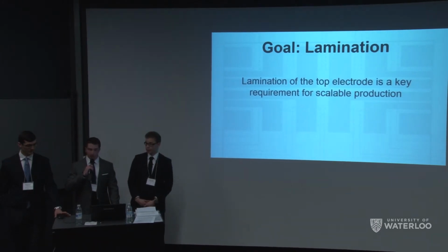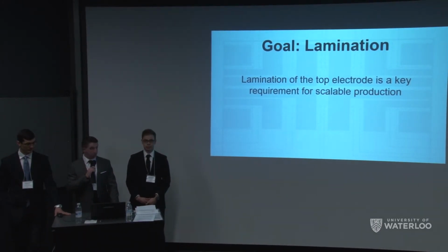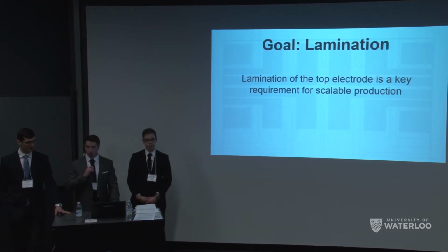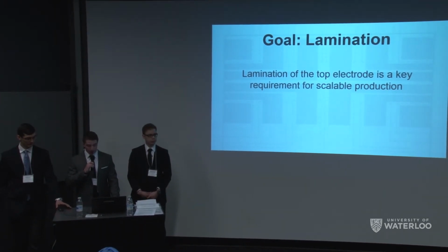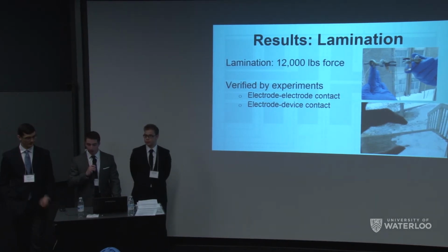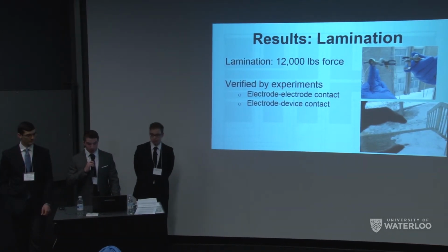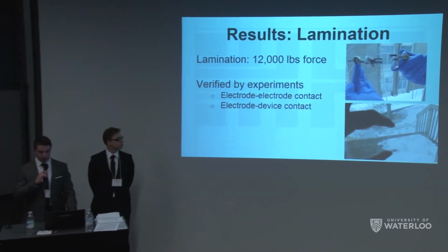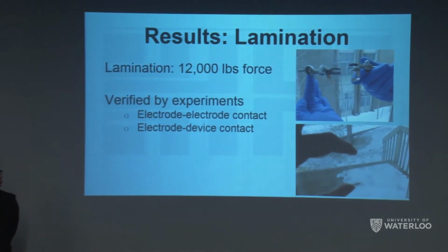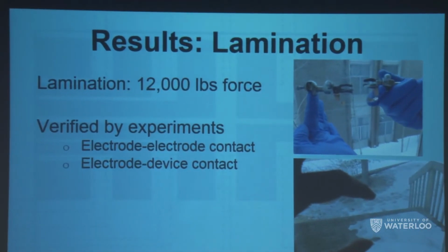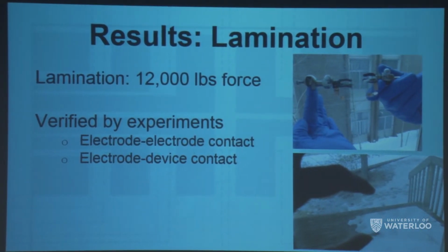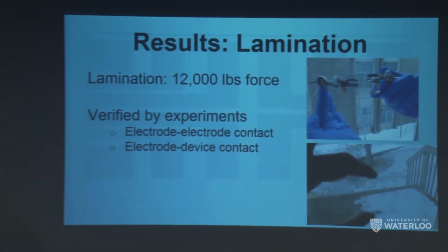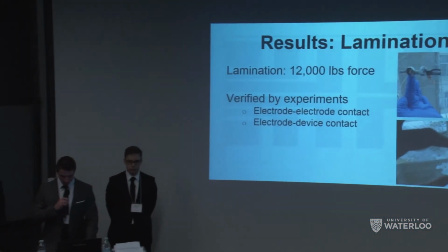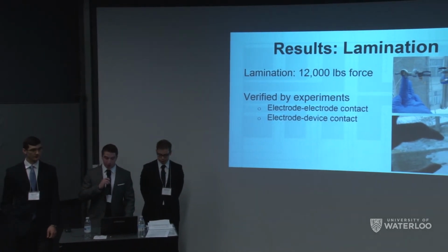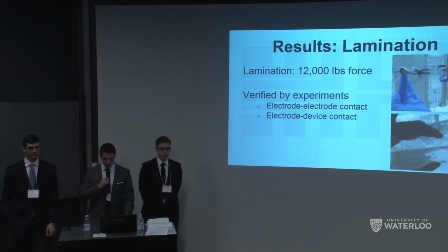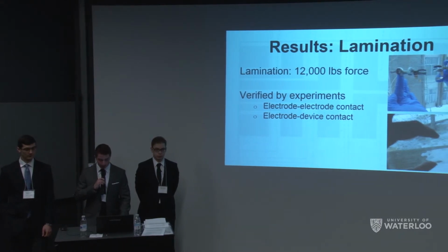A key design feature for scalable production was that we wanted to laminate the top transparent electrode onto a device. We approached this by taking a press and applying 12,000 pounds of force to push the two substrates together. We validated our lamination process in two ways. First, we just applied the force to ITO-coated glass and silver nanowire-coated plastic and checked to see if they adhered together with good electrical contact. The two substrates did adhere and were connected with a low resistance value of 250 ohms between the two substrates. In contrast, pressing together two non-flexible substrates, both ITO-coated glass, produced no electrical contact and they did not adhere.